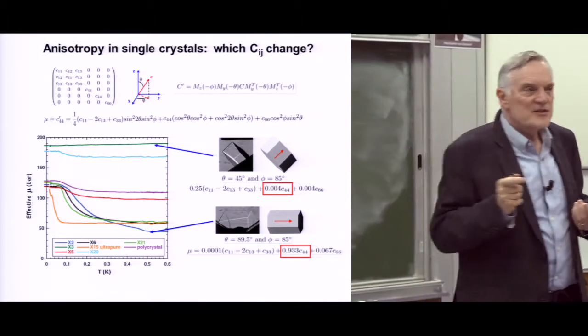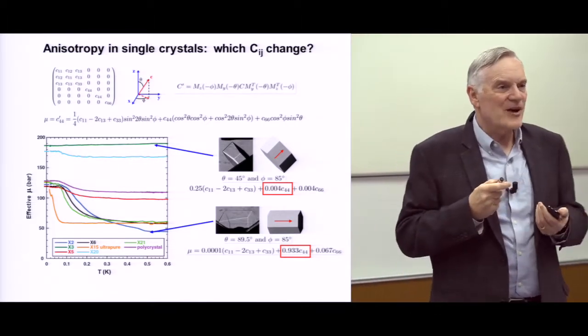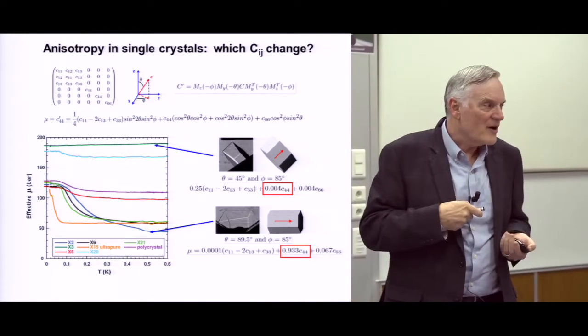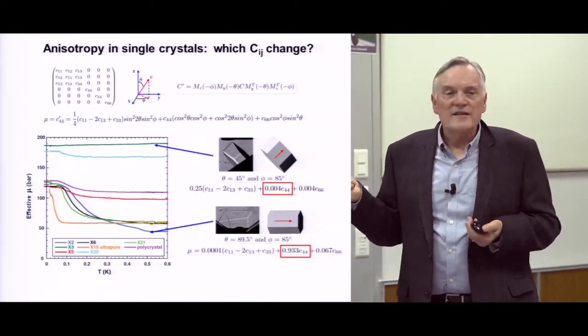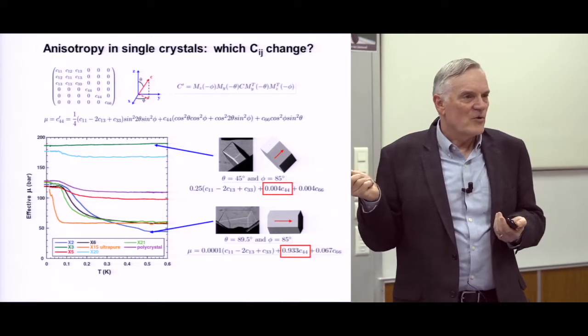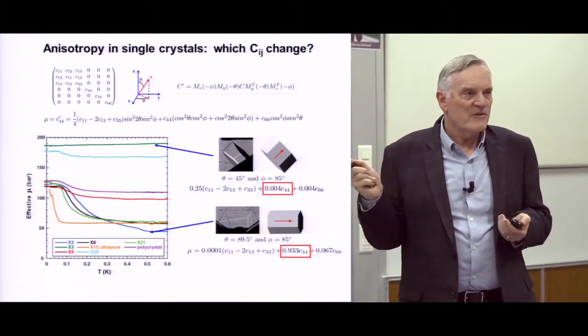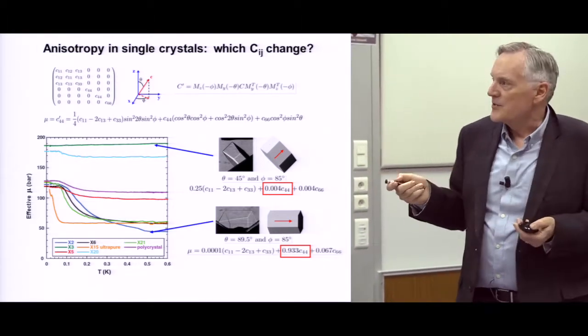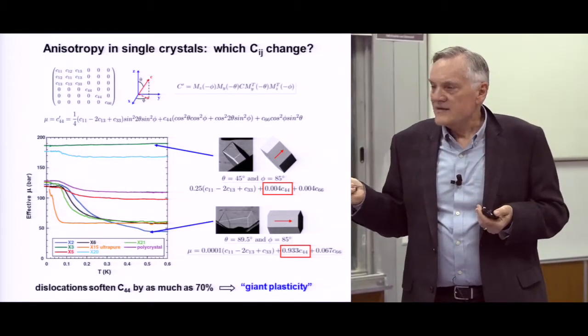So what this tells you is you're essentially measuring in a direction where you aren't sensitive to C44 and one where you are, and the only thing that's changing out of those five is the C44. One elastic constant out of all five is changing, the rest are doing nothing. So it's all in that particular plane.